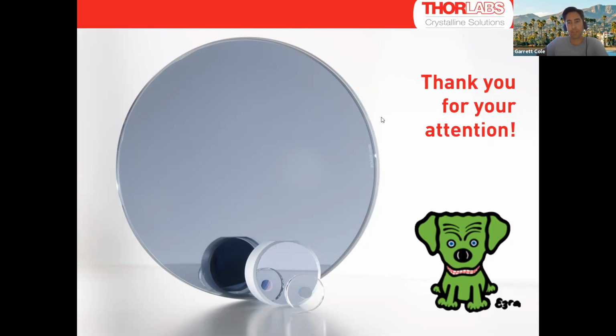When you have a high index of 3.5, your quarter wave condition is very narrow. It's only about 70 nanometers thick. And then your AlGaAs low index refractive index is about 3, so it's about 90 nanometers thickness. So the total stack is actually interestingly almost exactly the same as an ion beam sputtered multilayer: 5 microns around 1064 and up to 10 microns at say 1550 nanometers.